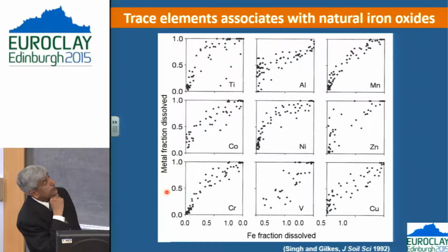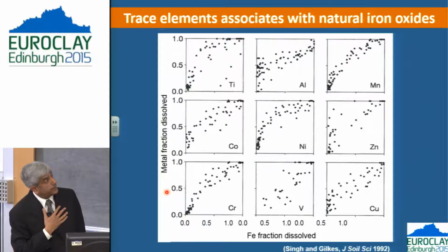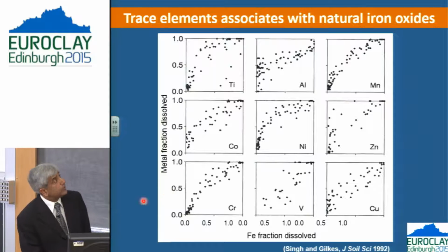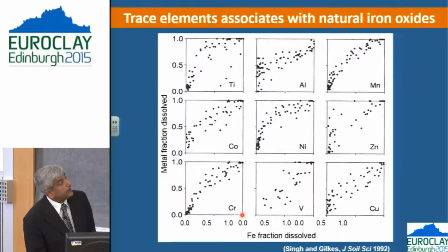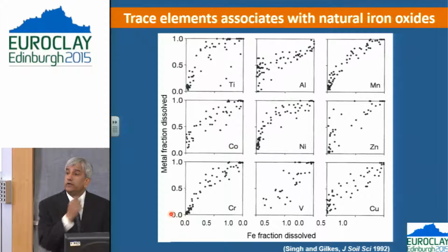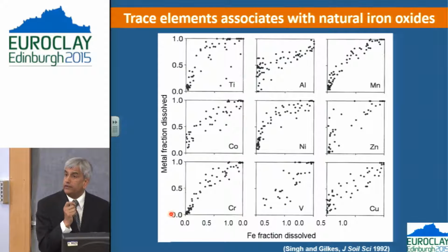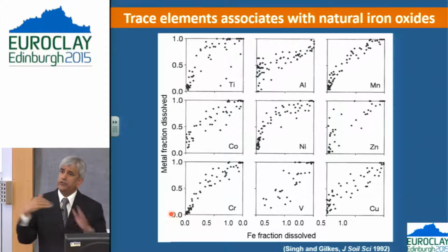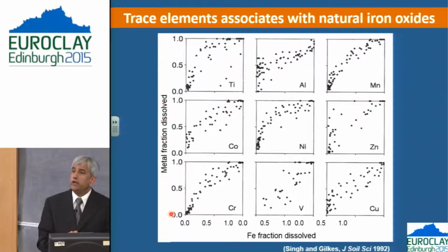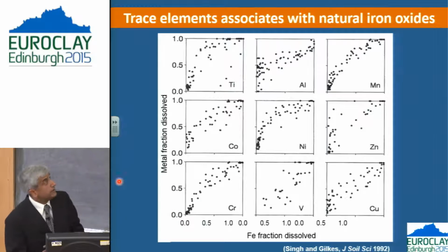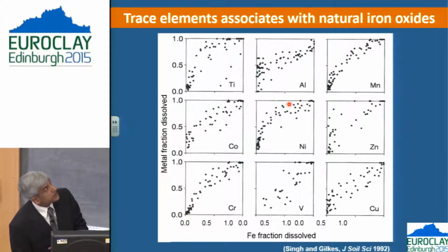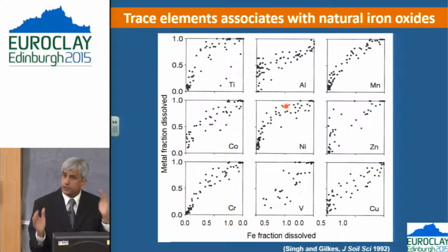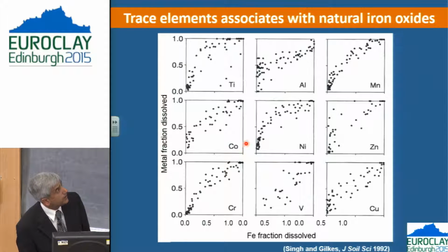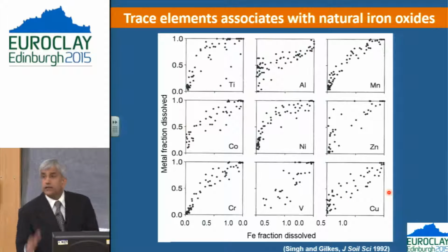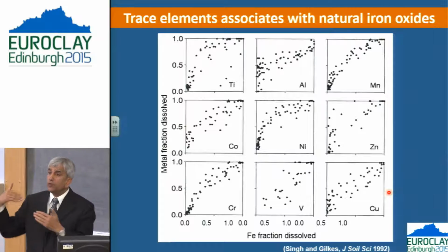And before I do that, I just wanted to put up this diagram where we looked at a lot of these trace elements and their association with iron oxides. These are the samples where we concentrated iron oxides, and then we dissolved the iron oxides in acids, and then saw how these elements dissolve in proportion to iron oxides or iron. And as you can see, for a number of these elements, the relationship is pretty strong. It's not a straight line, but nevertheless you can see in the case of chromium, nickel, manganese, cobalt, and to some extent aluminium and copper as well, that a lot of these elements are being released with iron.